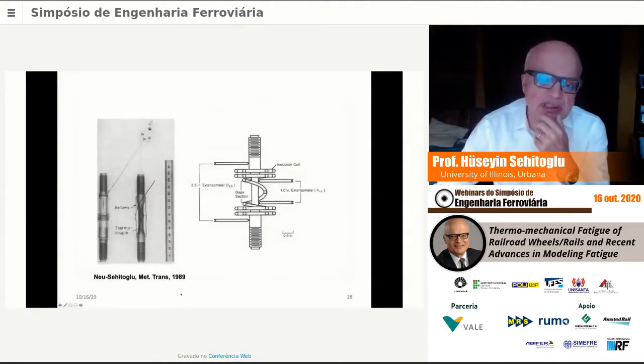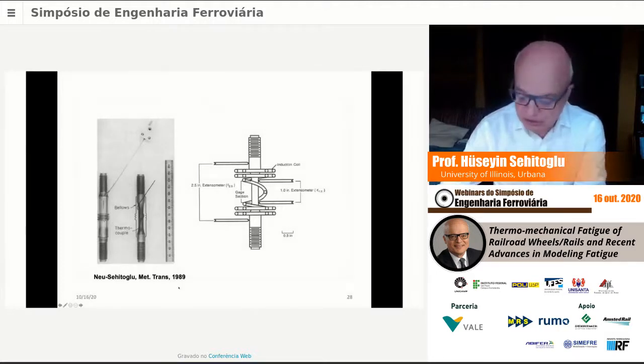Those helium experiments that I mentioned earlier, at that time, we didn't have a vacuum system. So what we did was we encapsulated the sample by making these bellows and trap helium inside, and then use an induction system to heat the sample. We had an extensometer outside the gauge section, but we calibrated it by putting an extensometer within the gauge section. So we were able to conduct those tests. So that's the thermocouple that goes inside these bellows here. This is, again, the very early work that we did, one of the first works we did.